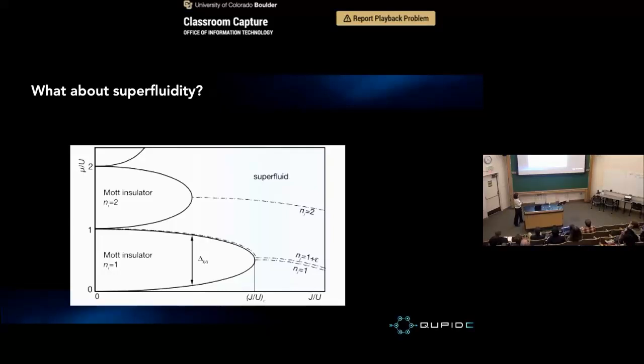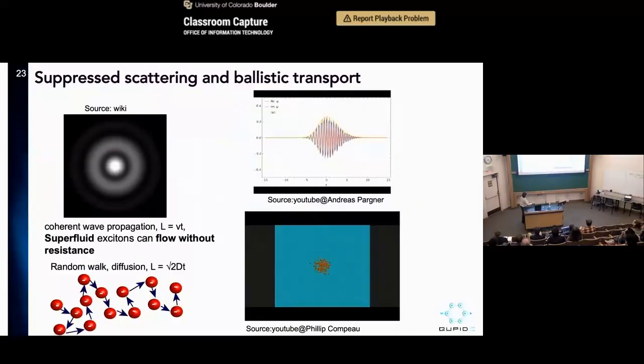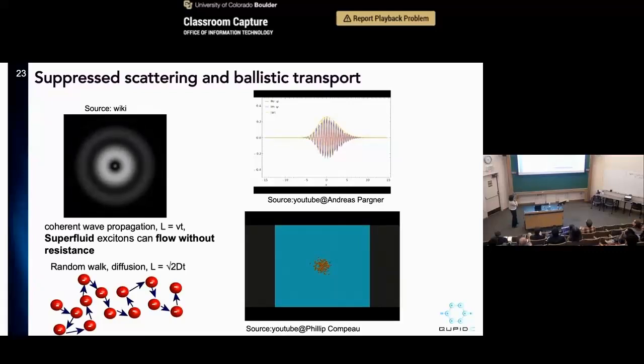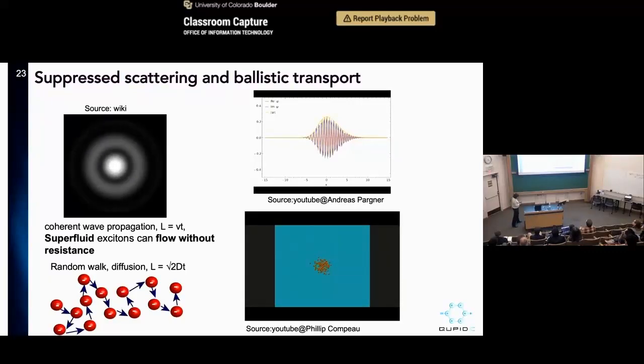The other thing that you might ask me is, shouldn't you also have superfluid when you are way underloading your lattice, which is like the 5% case? Why didn't you get superfluid? The reason is, again, J is probably smaller than thermal fluctuation or other scattering channels. So we actually just see diffusion, not superfluidity. And so the quest is to get to this phase of having this exciton as if there's no scattering.